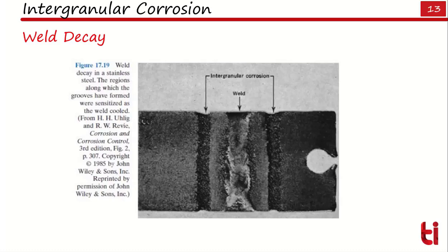If you are making the steel joints by welding, you are heating the metal in the sensitized temperature zone, and this leads to the formation of chromium carbide particles at the joint regions, and this could lead to the failure of the material from those joints, which is also referred to as weld decay.